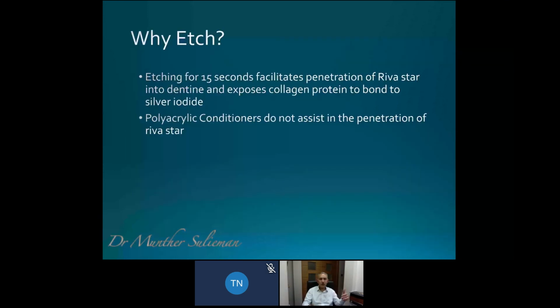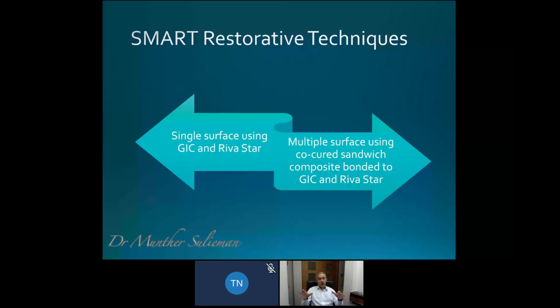I've already mentioned we etch. Why do we etch? It's to encourage the penetration of the silver iodide complexes deep within the collagen protein within the cavity to give you a good bactericidal seal. Using polyacrylics or polyacids as conditioners for glass ionomers doesn't really assist in that same fashion. They just don't have that same ability. And incidentally, I tend to etch even for glass ionomers normally, a very short etch, rather than use conditioners. So when we're talking about smart restorative techniques, if it was a single surface cavity, I would use Riva Star and a conventional glass ionomer.